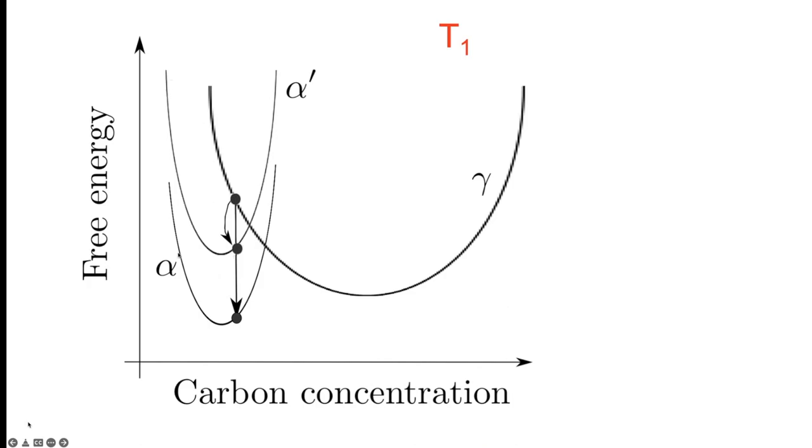And therefore, the martensite free energy curve is raised by that quantity in your CALPHAD calculation. And therefore, the net reduction in free energy is smaller than would be predicted just by the T0 condition and no change in chemical composition. Now, actually, the free energy required to stimulate martensite is even greater because we haven't accounted for nucleation as yet. But a rough value is that you need about 1,000 joules per mole of driving force before martensite is triggered. So you have to undercool the austenite to such a temperature that you get about 1,000 joules per mole of driving force in the case of the FCC to BCC transformation. Okay, so I'm leading you to how to calculate the martensite start temperature.